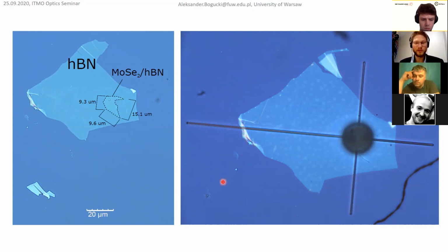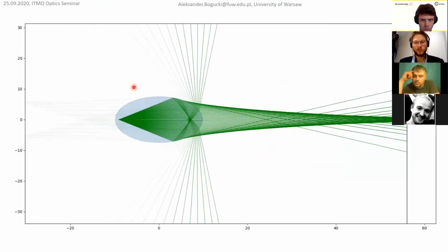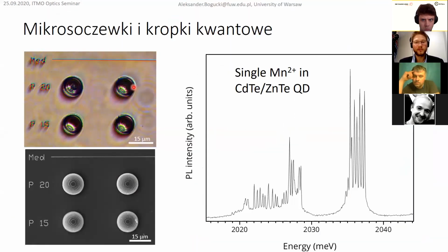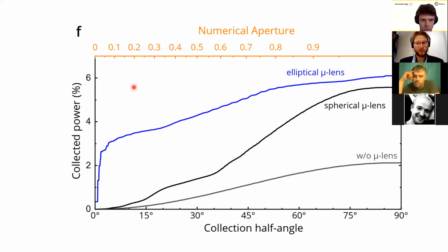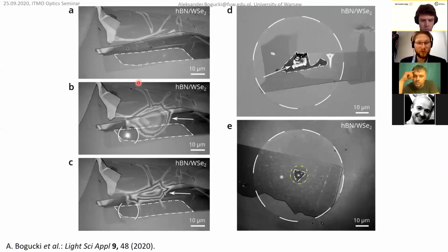But in our case, even printing at the beginning on transition metal dichalcogenides covered with hBN was pretty difficult, because it turned out that the quality of this hBN around is quite important. So here are examples. This is our very big flake on this dashed line, covered with hBN, which is not very smooth and not very flat. In exactly the place where this flatness was destroyed, you can see a big bubble starting to appear during the printing, right? And after printing, the microlens was printed.